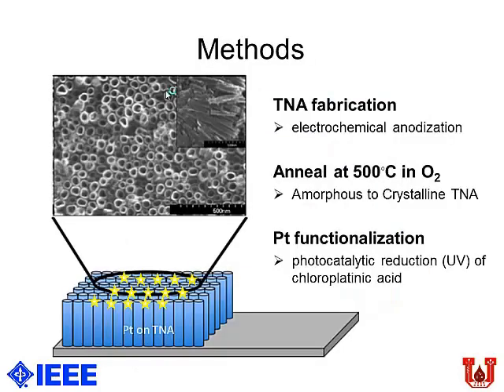So these are the fabrication methods. One key thing with this is we don't use any clean room technologies. Many of the sensors out there use clean room methods. The actual method by which we make titania nanotubes is a pre-existing reported mechanism. You just dip your titanium metal strip in an electrochemical bath, you apply potential, and basically you would have growth of these tubes. They're pretty uniform size.